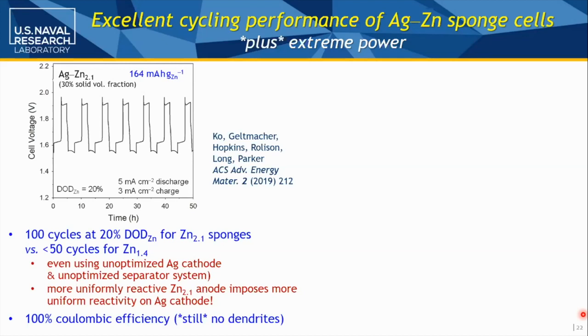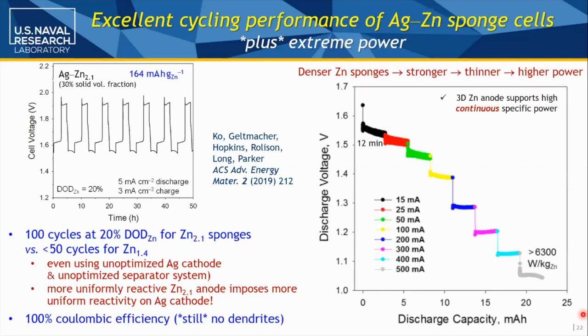And then that was sort of like the smack in the head, because of course, you have to think about how uniform is the current distribution between your two terminals. And if one electrode is misbehaving, like zinc is making dendrites, then the other electrode is trying to compensate for that now very irregular current distribution across the separator and the electrolyte. So if one electrode is being more uniform, you immediately take another electrode which is willing to act up and make it more uniform. So just that physical change in the zinc started to make even an unoptimized silver system behave. And now we're denser, we're stronger, we can thin it down, we can get higher power.